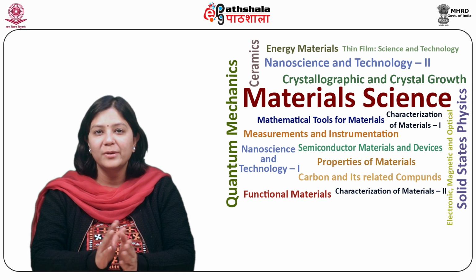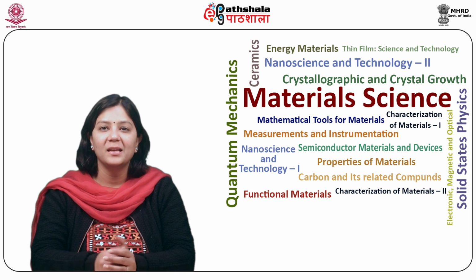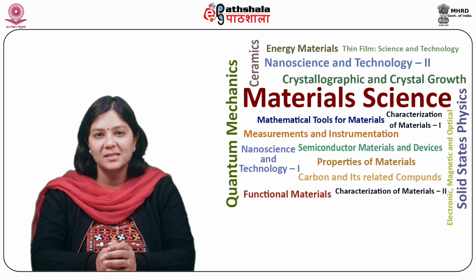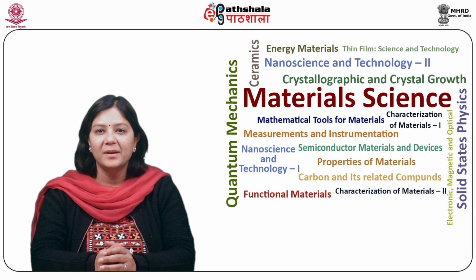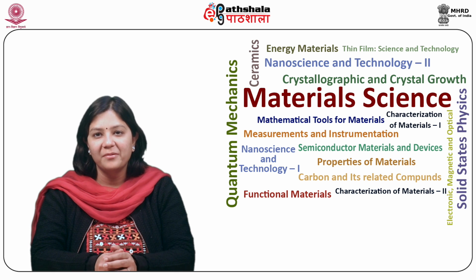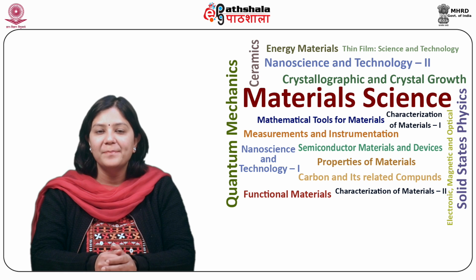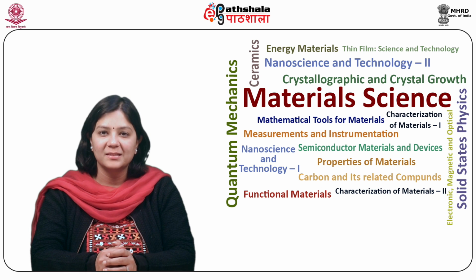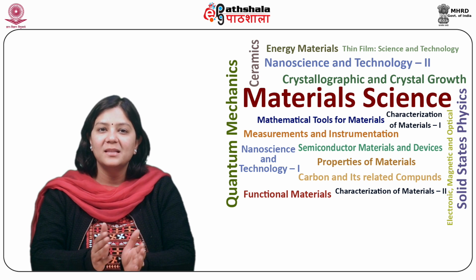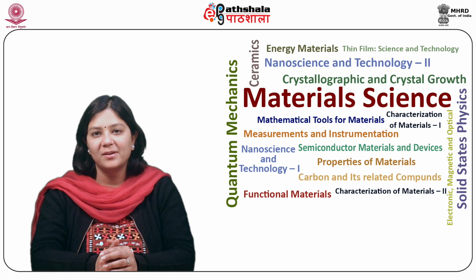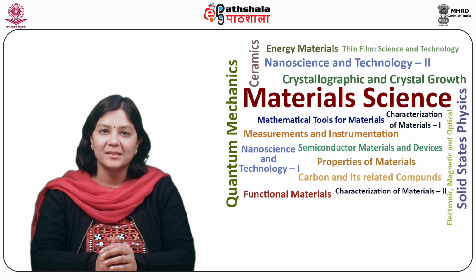It can also be coated with special coating layers to avoid reactions with the precursor material or gases. For example, during the growth of nitride and related compounds, the graphite susceptors may corrode owing to the presence of ammonia gas. To avoid this, the graphite is usually covered with protective coatings.